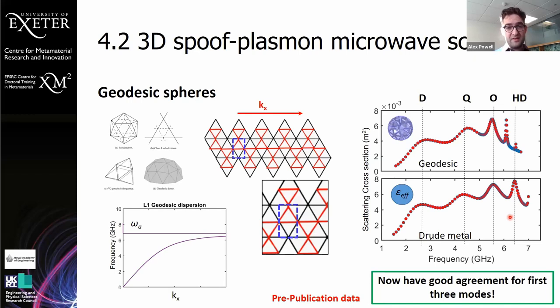And if we repeat the same simulations that we've done before, look at the wave vector going along this unfolded structure and use that to obtain an effective permittivity, we get very good agreement for the first three modes. And it's not until we get to the fourth mode now that we start to see less agreement between the structures. And we're currently having this fabricated by our colleagues at Loughborough. You could keep chasing this by having increasing subdivisions, but at some point you get diminishing returns, both in novelty and in difficulty fabricating it.